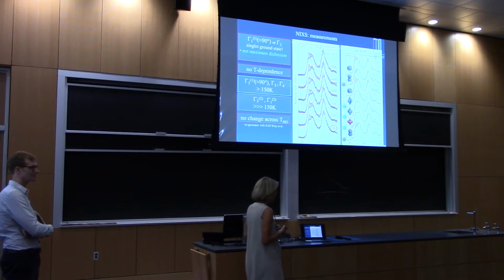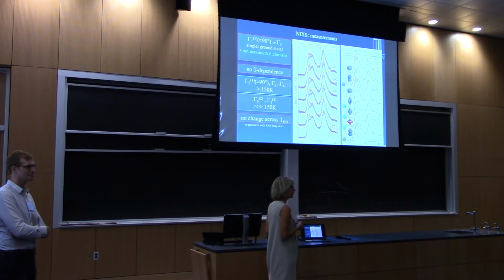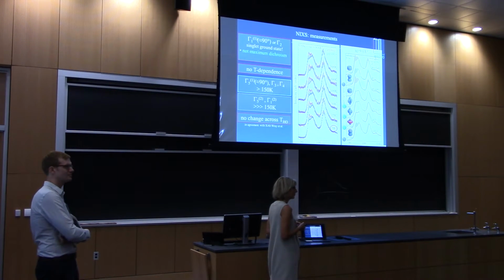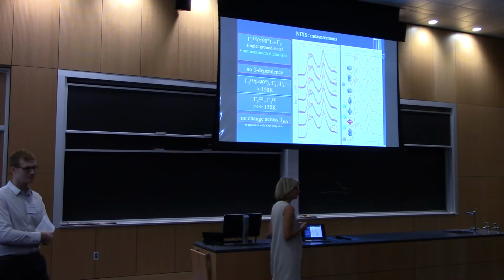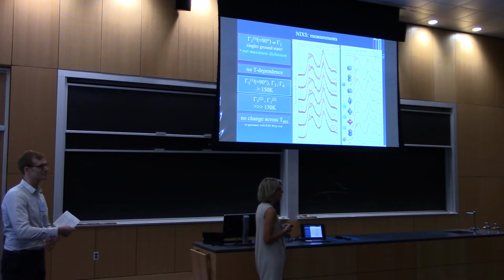Now, the entropy argument that you are bringing up is not based on any calculation. The proposal in Sean's paper is that what happens there is a density wave. The density wave opens up a gap. I think there's agreement across the board that the Fermi surface reconstructs, 40% of it goes away, and that's where the entropy is lost. So the entropy is lost due to the gap.